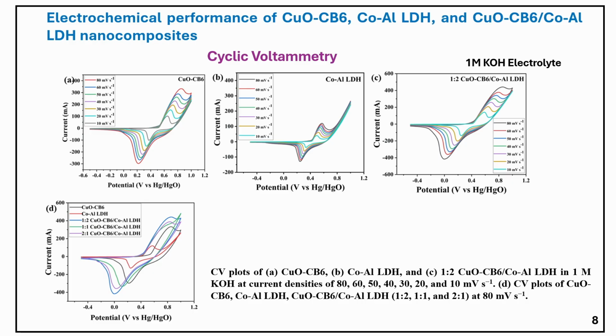The CV plots for the different nanocomposites showed varying results. The 1:2 nanocomposite had a significantly larger CV curve area compared to the pristine cobalt aluminum LDH and CuO-CB6 at a scan rate of 80 millivolt per second, which is a result of the deposition of CuO-CB6 on the cobalt aluminum LDH sheet.